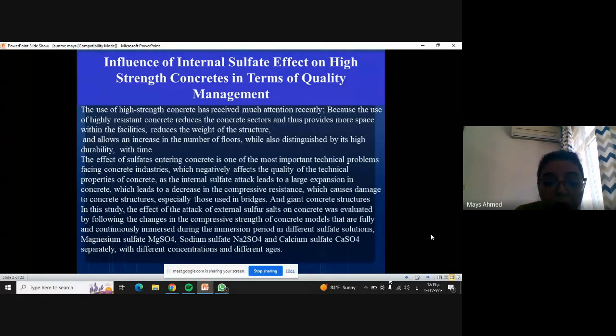concrete structures. In this study, the effect of attacks of external sulfate salt on concrete was evaluated by following the change to the compressive strength of concrete models that are fully and continuously immersed, during the immersion period, in different sulfate solutions like magnesium sulfate MgSO4, sodium sulfate Na2SO4 and calcium sulfate CaSO4 separately, with different concentrations and different ages.